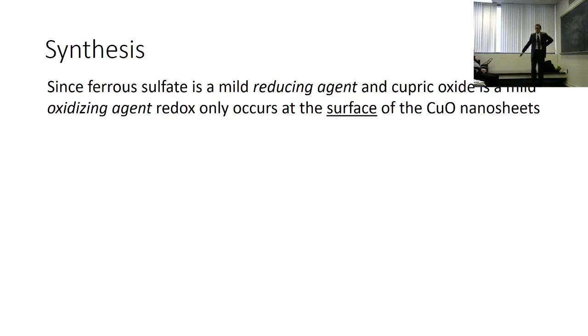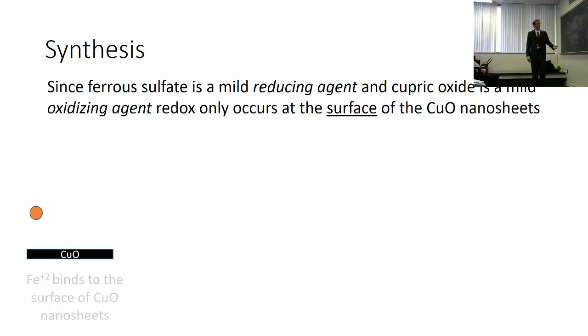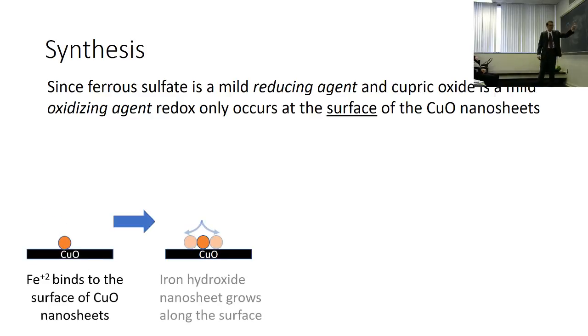Why does ferrous sulfate work? I tried ferric nitrate, so something with Fe3+. That didn't work. So it's not just iron that does this. There's something special about ferrous sulfate. And if you look up what ferrous sulfate is, it's a mild reducing agent. Copper oxide is a mild oxidizing agent. We know what happens when you mix oxidizing and reducing things. You get redox occurring. So what I think was happening was this Fe2+ is binding to the surface of copper oxide, and then it's being oxidized.